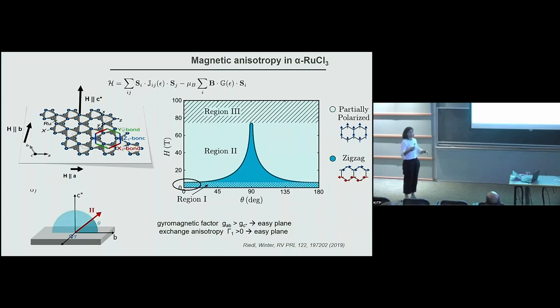So if one wants to go away from the zigzag long-range order in perpendicular magnetic fields, one should apply magnetic fields of 70 or 80 Teslas. So that's why most of the experiments are done by putting magnetic fields parallel to the plane. However, many models are predicting very exotic phases with magnetic fields applied perpendicular to the plane.